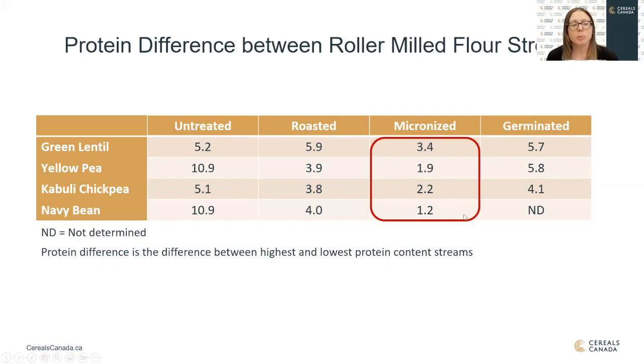The reason I'm pointing this out is that if your goal was to create a targeted protein content ingredient from the roller milled streams, it might be challenging once you start applying some of these pre-treatments, because you're getting less variation. I'm not sure exactly why this happened. However, it's likely due to some changes in seed hardness or changes in the way that the seed is fracturing during milling, causing the protein to distribute differently.